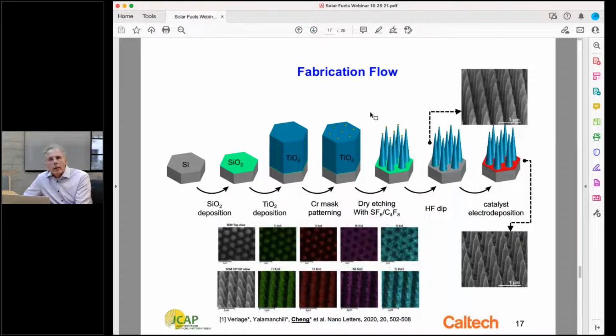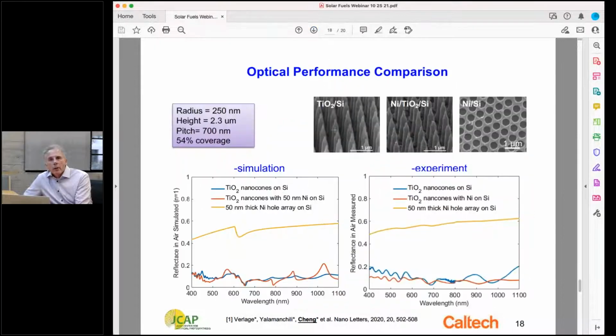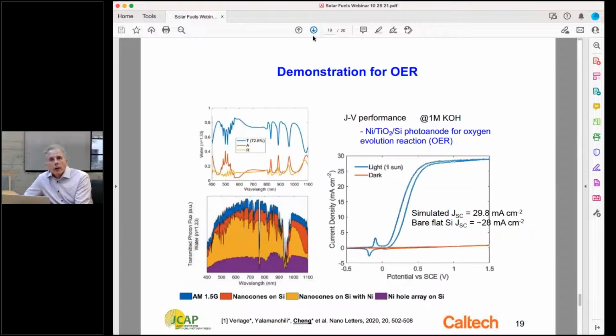This is what the structures look like when they were fabricated with titanium dioxide. We tested these and showed that the nanocones gave, in experiment, reflectivity and transmittance results very similar to the predictions. This was also used in an OER photoanode application, where silicon was used as a photoanode, coated with nickel and titanium dioxide. In this case, the photoanode produced a photocurrent density during OER that was indistinguishable from that of a bare flat silicon photoelectrode.